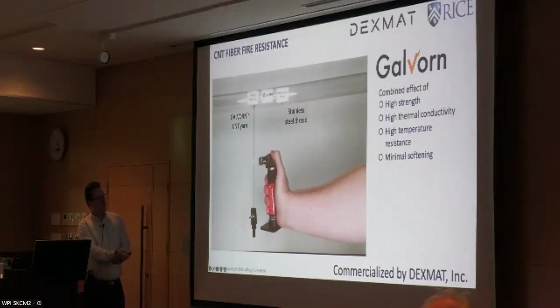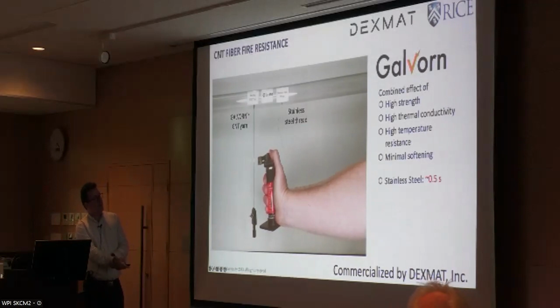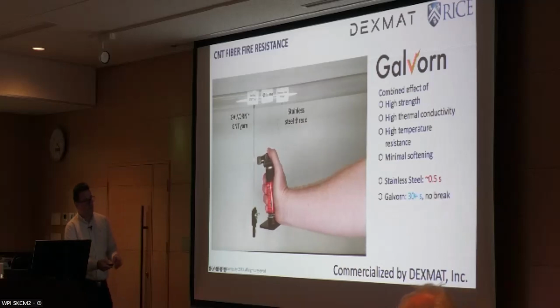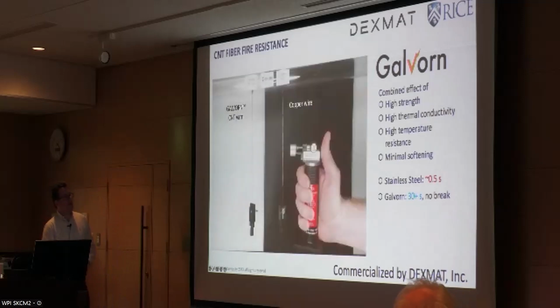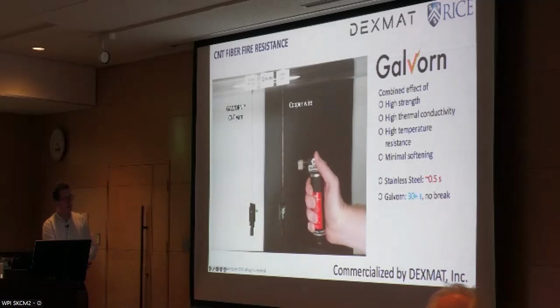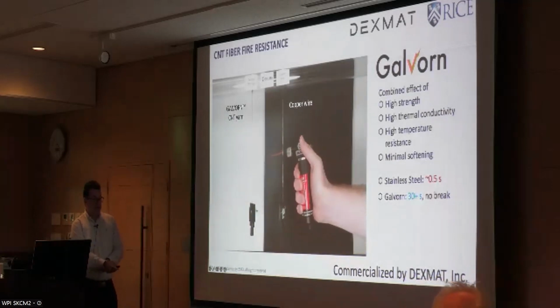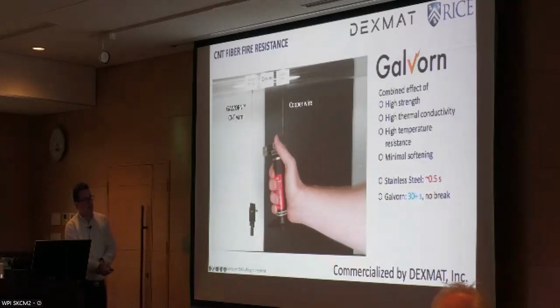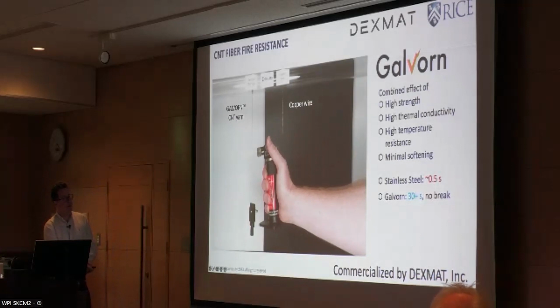Another thing here is resistance to heat. That's a butane torch or propane torch. What you see is a stainless steel thread that resists for about half a second. Galvorn CNT yarn. Now, Galvorn is the trademark name of this material by one of the companies that makes it. Resists well over 30 seconds. If you do it against copper wire, copper resists a little longer than steel because it actually has higher thermal conductivity. It is about dissipating the heat away, but it's still talking about somewhere around 6 seconds, whereas the nanotube wire doesn't really budge.